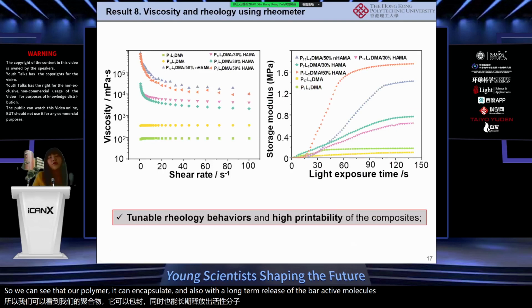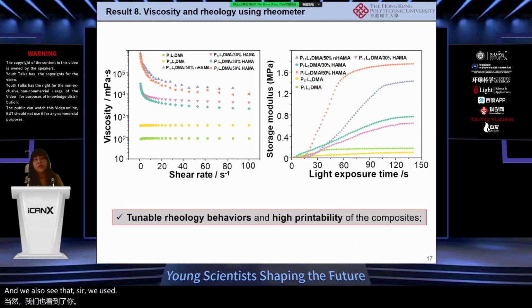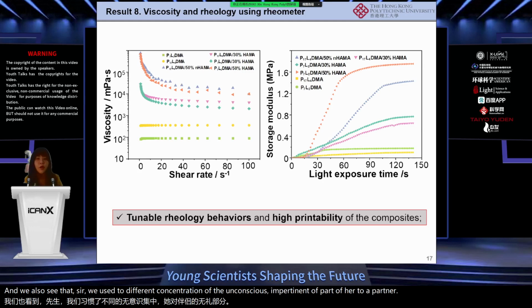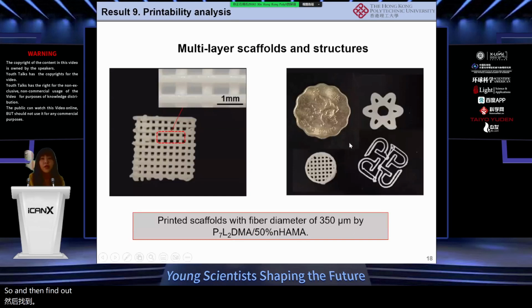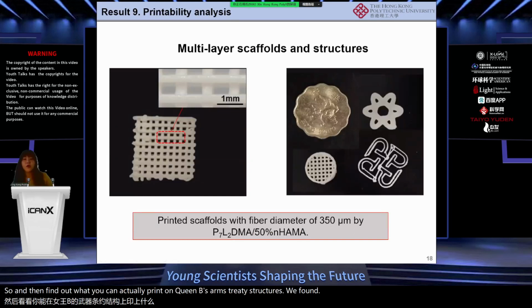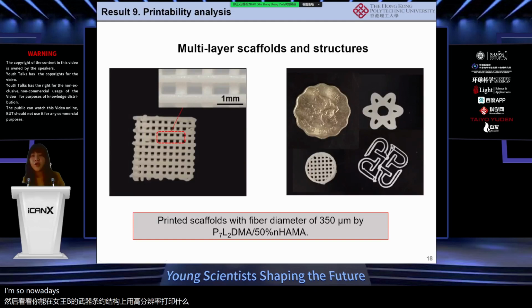And we also see that we use different concentrations of the hydroxyapatite nanoparticles to polymer, and then we can adjust the viscosity. And then we find that we can print these 3D structures with high resolution. Nowadays we are using another 3D printing method called DLP. So now we can print with a resolution of about 100 micron.